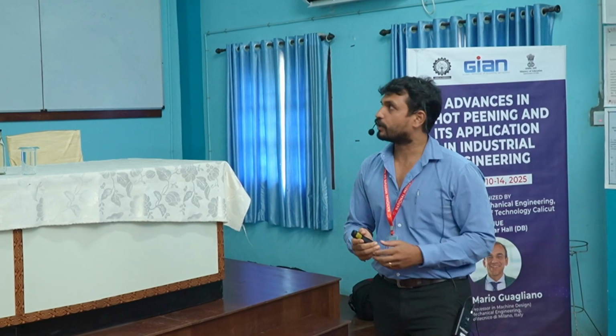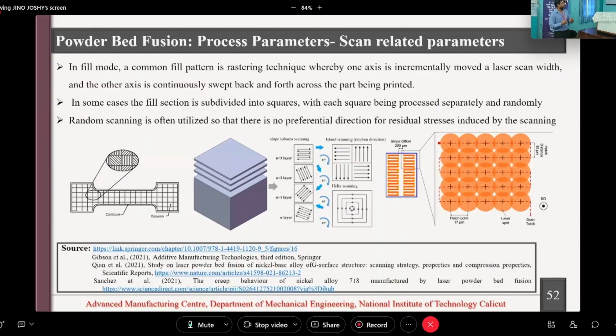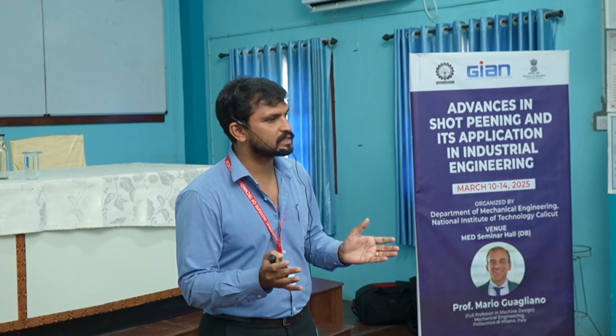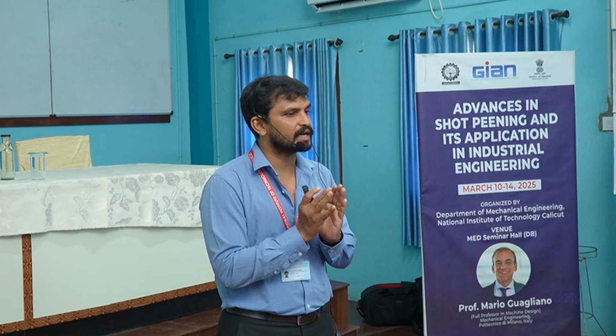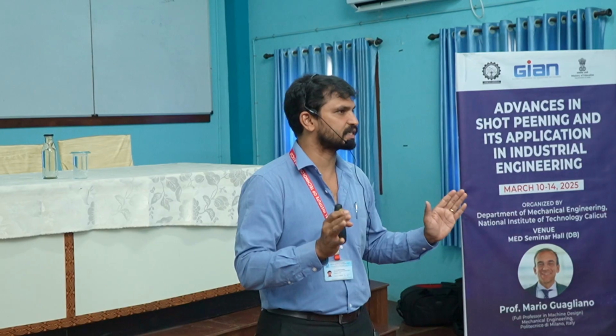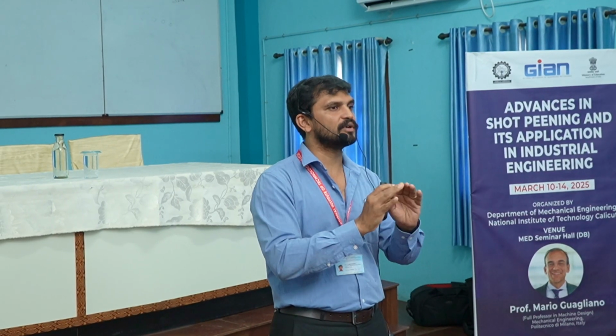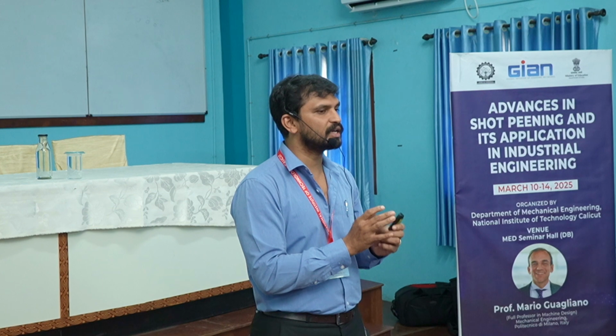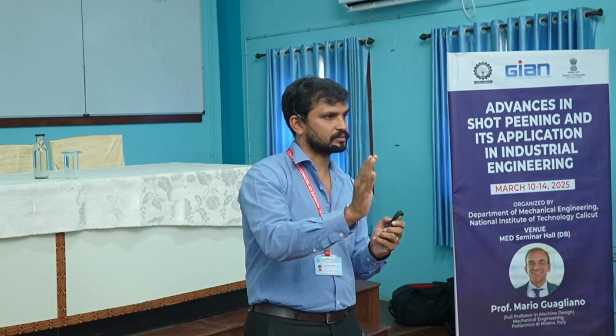And in fill mode, like I have already told, the common fill pattern is a rastering technique whereby one axis is incrementally moved a laser scan width, and the other axis is continuously stepped back and forth for printing the components. That is called the fill mode. Random scanning is often utilized so that there is no preferential direction for the residual stresses induced due to the scanning. So this is what I previously told, that we will always be doing a random scanning. That means we don't want the residual stresses to be induced by the scanning in any one direction.